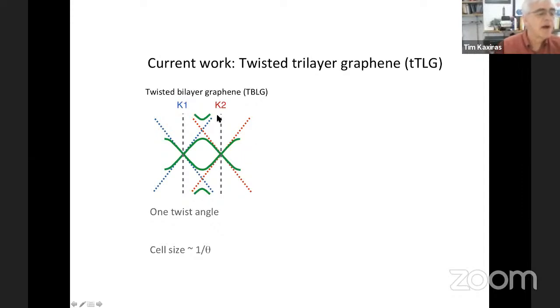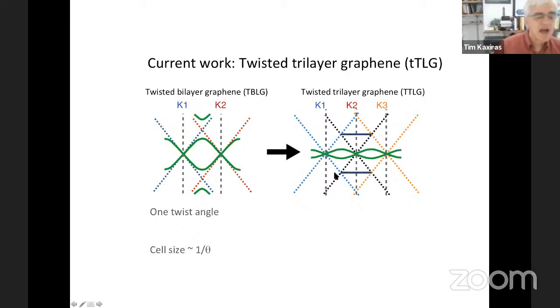Just to make a comparison, here's the twisted bilayer graphene system again. I showed you this picture earlier. I believe you should be familiar with this. The 2 Dirac cones, red and blue, intersecting here and producing the flat bands. There's 1 twist angle, and the cell size, the real space configuration, the Moiré pattern, is proportional to 1 over the twist angle theta.